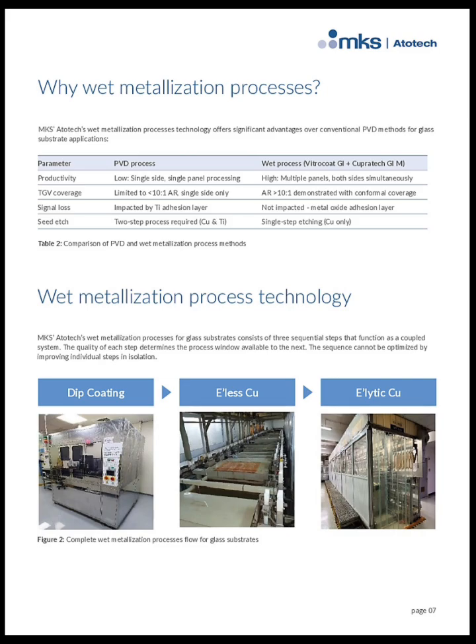Wet metallization processes provide significant benefits compared to traditional physical vapor deposition. They enable higher productivity through simultaneous double-sided, multi-panel processing and achieve conformal coverage for aspect ratios exceeding 10:1. Unlike PVD, wet processes avoid titanium adhesion layers, reducing signal loss and simplifying seed layer etching to a single copper-only step. The process flows through dip coating, electroless copper plating, and electrolytic copper plating, each contributing to robust adhesion, uniform seed layers, and void-free via filling.